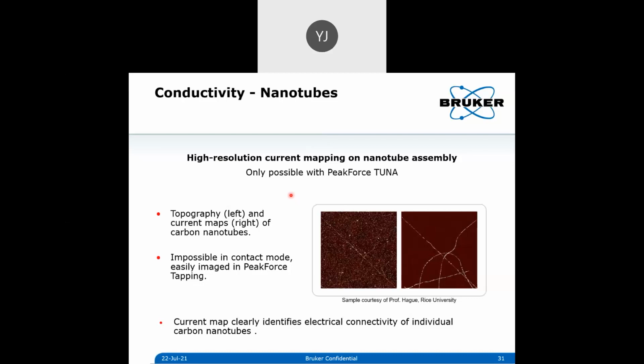So here are some challenging samples. This is a nanotube that's just lying on a substrate. It's not fixed or anything. This is the topography image. And when you do the current image, you can see a very nice image of the current that's flowing only through the nanotube and zero current on the substrate, right? If you're doing contact mode imaging, you can easily dislodge these fibers which are just resting there. You just scan with contact mode, you will drag them across, and you can even see that the current is not uniform across the nanotube, right?